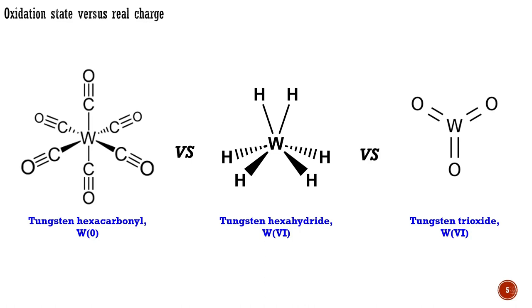In real terms, tungsten(VI) hexahydride is probably more reduced and more electron-rich than tungsten hexacarbonyl, which is formally tungsten(0). Carbon monoxide groups are excellent pi acceptors, so the metal in tungsten hexacarbonyl has a much lower electron density than a free tungsten 0 atom. On the other hand, the tungsten-hydrogen bond in tungsten hexahydride is only weakly polar, and so the polyhydride has a much higher electron density than the tungsten(VI) suggested by its oxidation state. For this reason, in organometallic chemistry, the use of the term formal oxidation state is more appropriate.